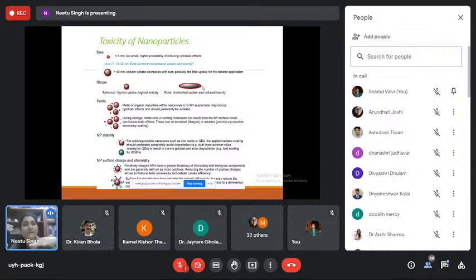However, they cannot enter inside because they're too large, and that is why the uptake is diminished. There was a science paper, not a recent one, but about a decade ago, which talked about how they actually get inserted inside like a needle. If the thickness is really less, like a few nanometers, then it becomes almost like a needle, and it can pierce through the cell membrane, which can actually cause toxicity.